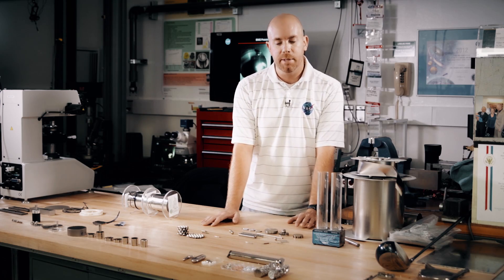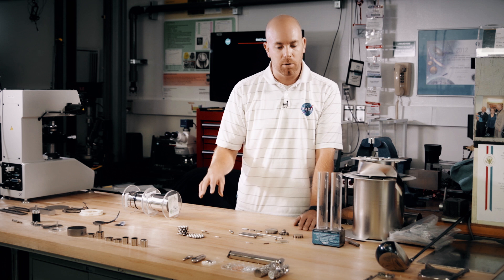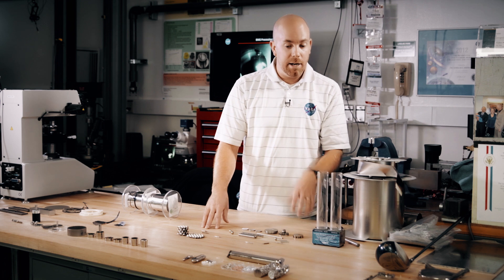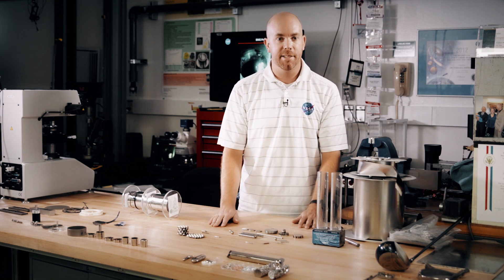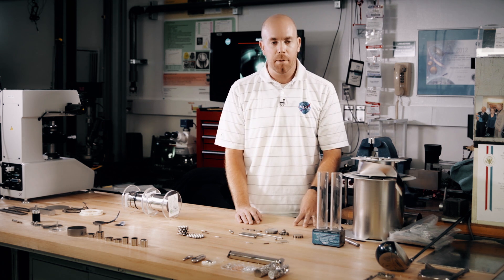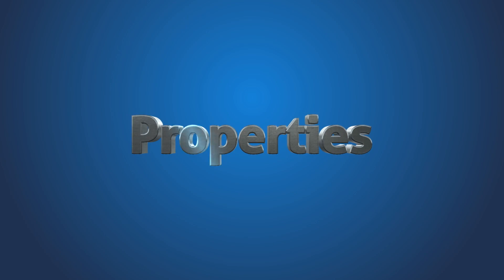The true advantage of using metallic glass compared with titanium — which is a close crystalline alloy — is that metallic glass, being a low melting temperature material, can be injection molded into parts like plastic. Except when you take a metallic glass out of a mold, by the nature of it being frozen into a glassy state, you get properties out of the part that are similar to titanium or steel. That is an absolute revolution in the way that you make small complex metal parts.